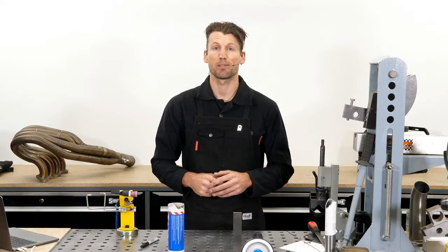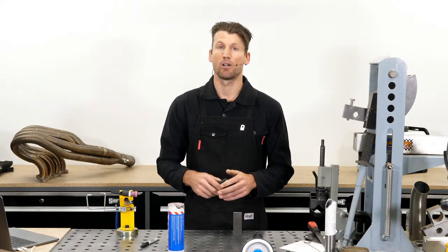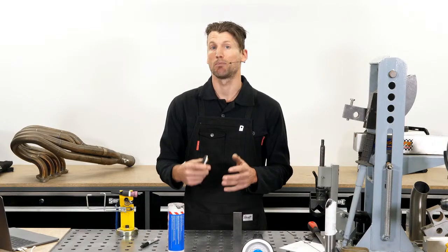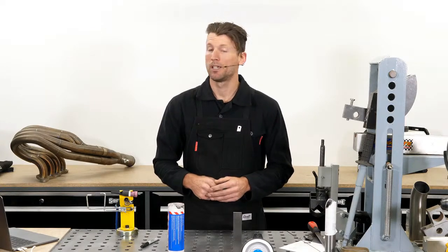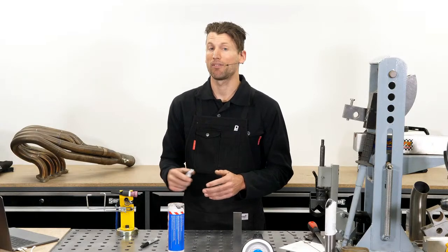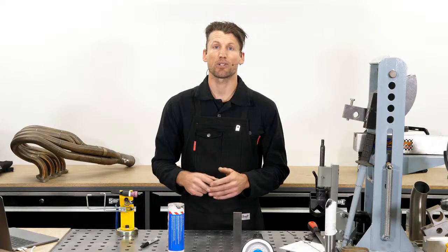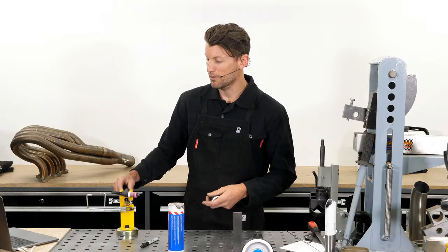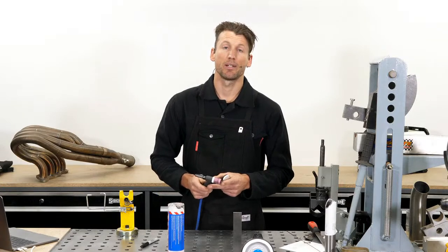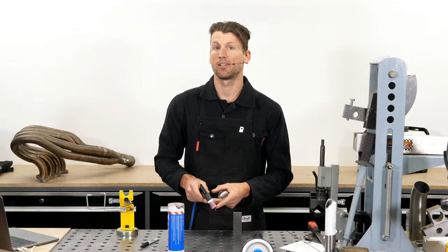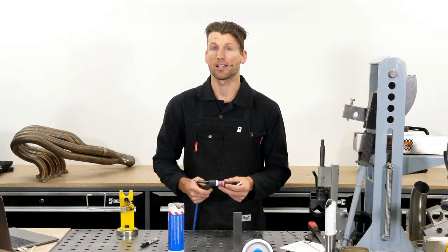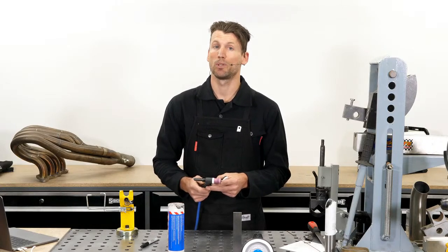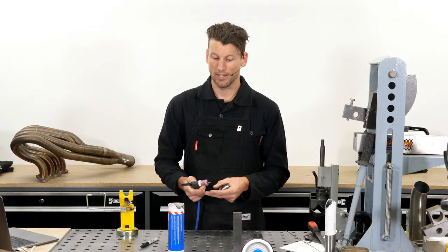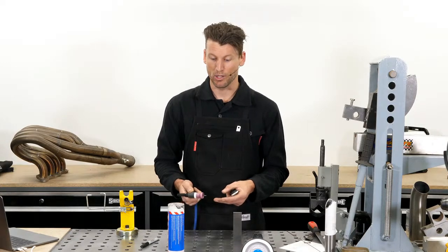Simon, this is a really, really good question, and I see it quite often, and you'll see it all the time with multi-process machines. That involves maybe a MIG welder also having the ability to TIG weld, which a lot of them do. Now, the problem with this is they won't be high frequency start, which means that they'll be a scratch or a lift start TIG. So what that entails is, without high frequency start, you will have to touch the tungsten onto the workpiece to start the arc. Nearly all of these machines will not be compatible with alloy welding either, so you're really limited in the amount of jobs that you can do.